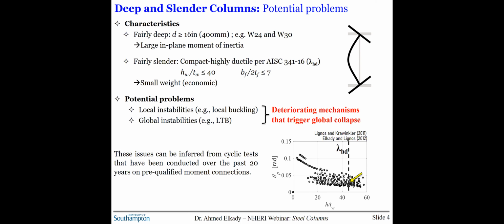Now, this issue can actually be inferred from past cyclic tests on steel beams. For instance, looking at this plot on the right here, we observe that beams close to the slenderness limit may develop limited plastic rotation capacity of about 2 or 3% radian prior to local buckling, and that's without axial loads. So you can expect this issue to be more critical in columns.